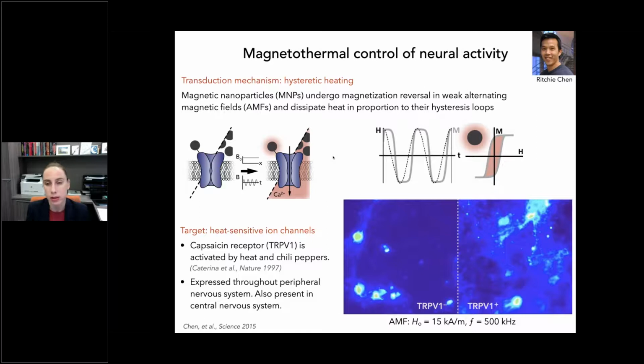And the reason for that is the capsaicin receptor, TRPV1, that is expressed in the cells in your tongue, but also is expressed across your nervous system. So this same receptor responds to both capsaicin and heat. And if we sensitize neurons to this receptor, we can then surround them by magnetic nanoparticles and then apply a magnetic field. And only if our cells are sensitive to heat will we see them firing in response to this really weak but fast magnetic field through magnetothermal stimulation.